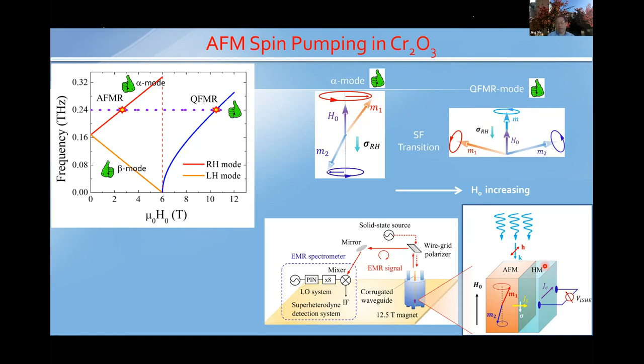We use tantalum and platinum. As you all know, these two metals will generate, for the same spin polarization, opposite signs in the inverse spin Hall voltage. So this would be a nice way of telling whether you have a spin current or some other spurious signal from the circuit. Okay, so these are the parameters that we use at Santa Barbara.